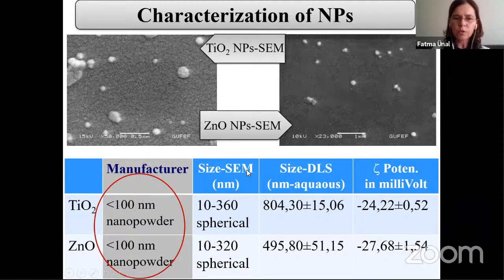For example, scanning electron microscopy showed that both of these nanoparticles were spherical in shape, and they were between 10 and 360 nanometers for titanium dioxide nanoparticles, and between 10 and 320 nanometers for zinc oxide nanoparticles in dimensions. Dynamic light scattering showed that these nanoparticles have 804 and 495 nanometers in size. Their zeta potentials were determined as -24 and -27 for both nanoparticles.